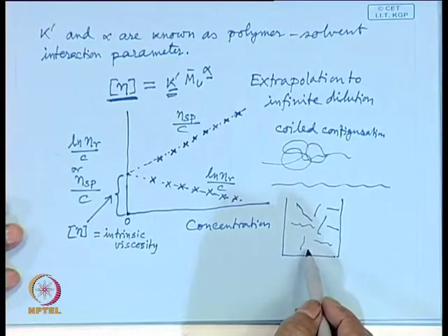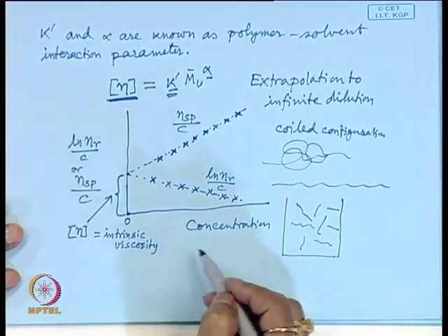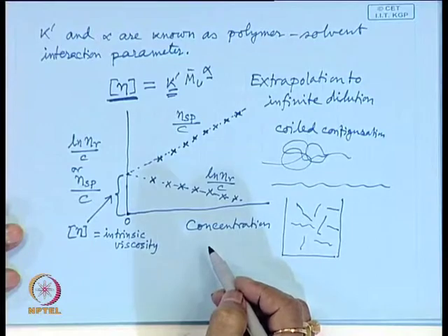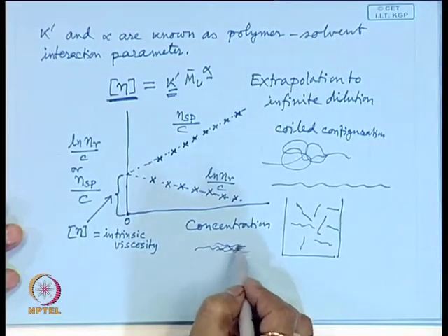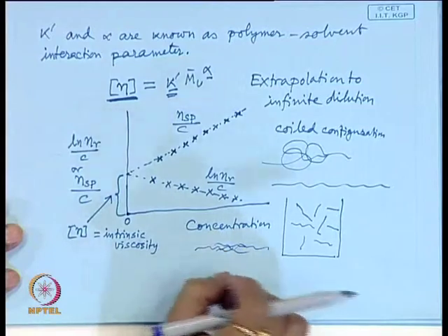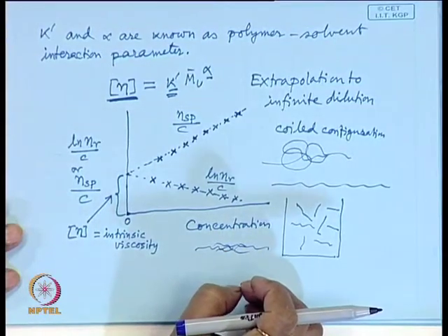Why is it necessary? When these polymers are flowing in a solution state through a capillary, if one polymer molecule remains attached to or very close to another polymer molecule, then the resistance offered against flow will be more. Now, here you get one more concept.